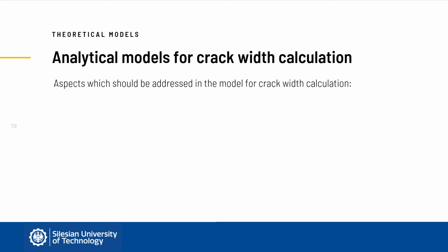Numerous methods for crack width calculation can be found in the literature of the subject. There are a lot of similarities between them. However, there are also discrepancies which must be accounted for in the robust use of these methods. In general, the following aspects should be addressed in the model for crack width calculation. The effective tensile strength, so the strength for which cracking occurs.